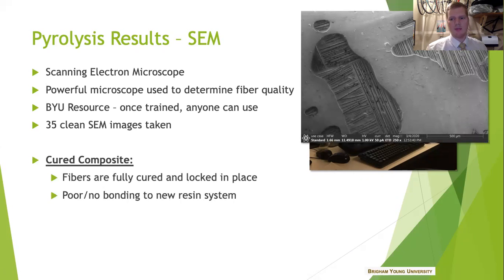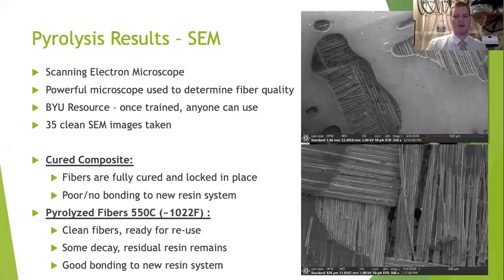Here you can see carbon fiber that was fully cured. And you can almost see that these little filaments, it looks like they're floating in a bath or a pool of this resin. That's how it looks when there's good resin dispersement there. However, if you were to just try to bond new composite together off of this panel, you would not get great bonding because they're already all filled in. With the pyrolysis process, you can see that that really opens up, and that these fibers are, even though there's a little bit of this residual resin left over, they are really ready to accept some new resin system that can bond in there. So that's a very clear before and after picture of what pyrolysis does at a really small scale, so you can see it.